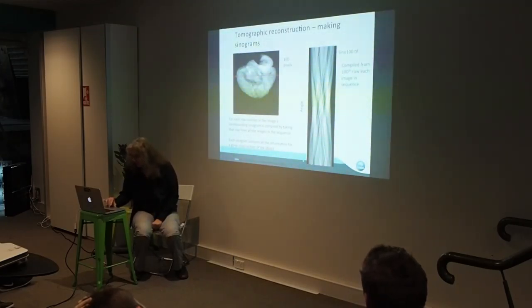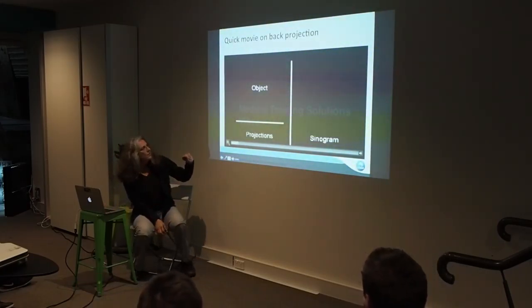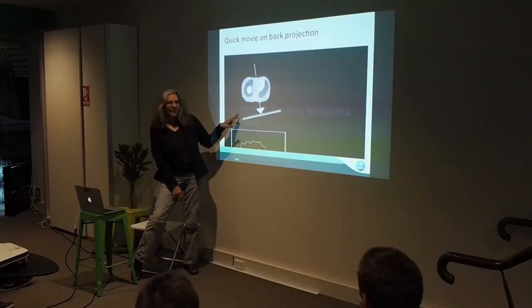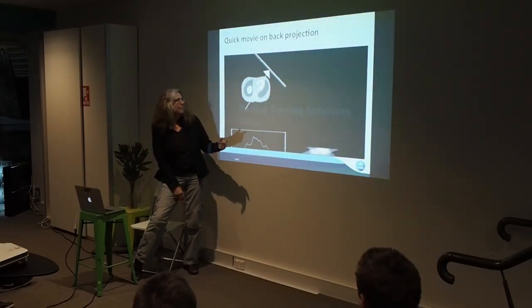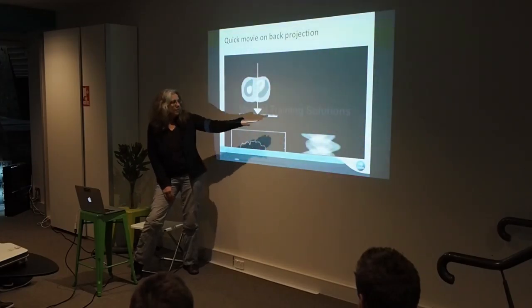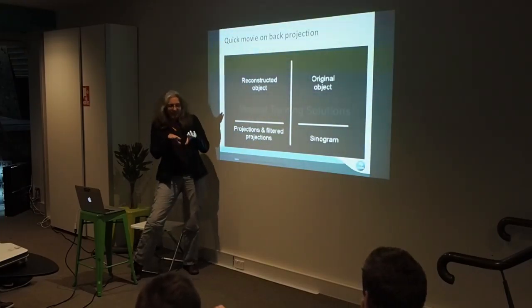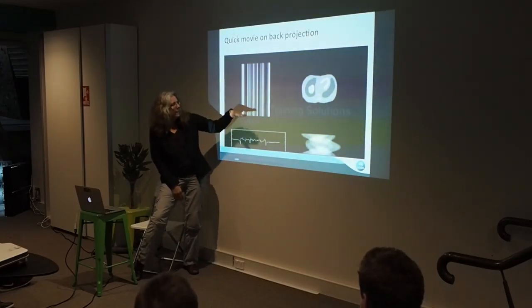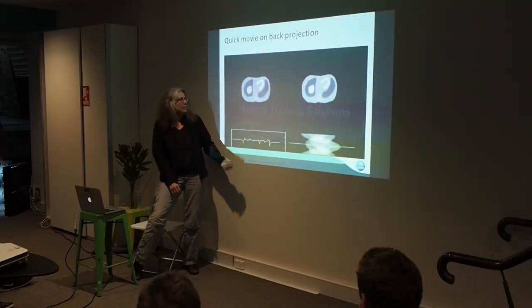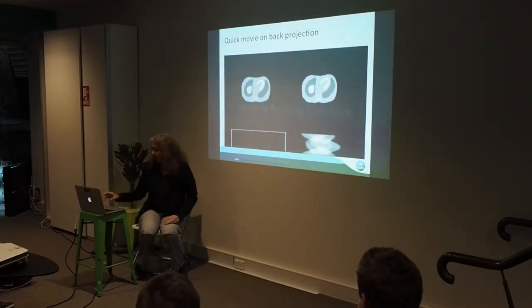From that sinogram, you can actually reconstruct what's in that slice — that cross-section of your sample. And if you do that for all layers you get a whole 3D model. So I've got a little movie here illustrating that. This is one layer of the object and the corresponding pixels on the CCD. The object is rotating round, building up a sinogram corresponding to the information in that layer. Taking that sinogram, you can project it into a kind of plane. Mathematically it works out — with a few extra twists I won't go into — and it builds up the cross-section. With a whole bunch of those, you've got your 3D model.